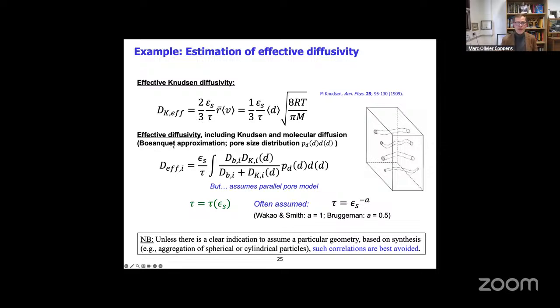If you include Knudsen and molecular diffusion, you can include a pore size distribution as well. And if these pores can be considered parallel, you can easily integrate. And then the tortuosity here invokes other facets of the pore tortuosity. However, this assumes a parallel pore model. And so using this in practice, often one assumes some type of relation, that fudge factor, as Aris called it, for the tortuosity. But through many types of both experimentation and some types of models, it was found that you can find relations between the tortuosity and the porosity of these materials.